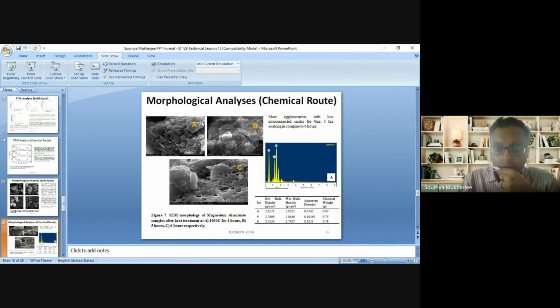For the chemical route, we are not getting that variation of cuboid to flaky structure, but it is dense and agglomerated, and in some portions we get interconnected cracks and porosity. EDAX analysis confirms the presence of magnesium aluminum oxide only, and we have calculated the density for 4 hours, 5 hours and 6 hours along with apparent porosity. These variations are almost in line with the morphological analysis.